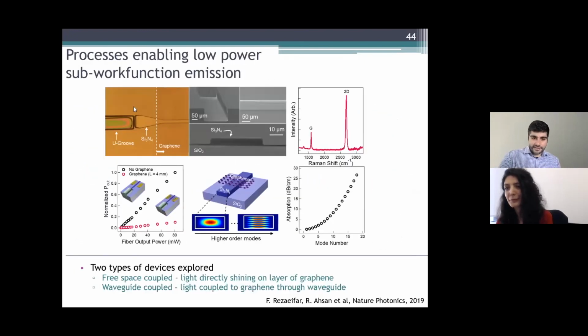So this left-hand image is an optical image of the silicon surface with the silicon nitride waveguide and graphene. What you see over here is a U groove that we dry etched into the silicon, and then we take some epoxy, put it on the stripped fiber, and put it in there, and then we couple the fiber into the waveguide, and then we let the epoxy dry, and so it holds it in there. Then we stick that whole thing into a vacuum chamber, because obviously it's electron emission, so everything's done in a high vacuum chamber. So that's the answer to that.